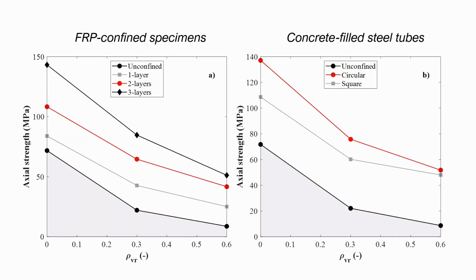Also on the left side, I'm plotting the axial strength against the rubber content. So the bottom line is the unconfined strength, and just shows how having one layer of FRP confinement increases the strength up to having 3 layers, which shows quite decent strength even for the specimens with the highest rubber content.